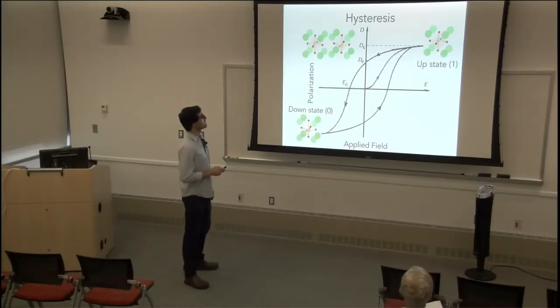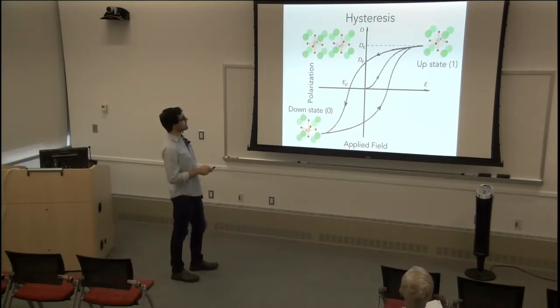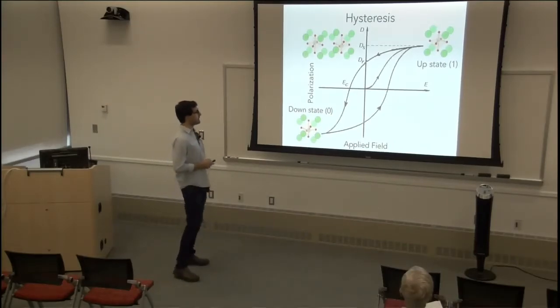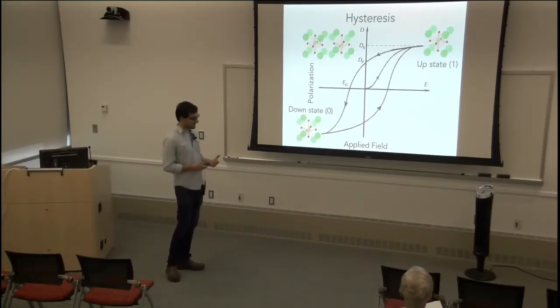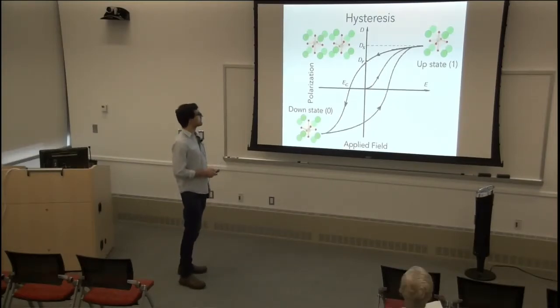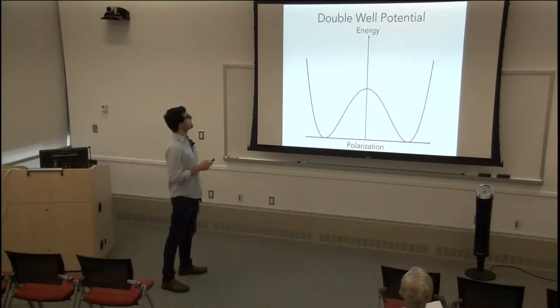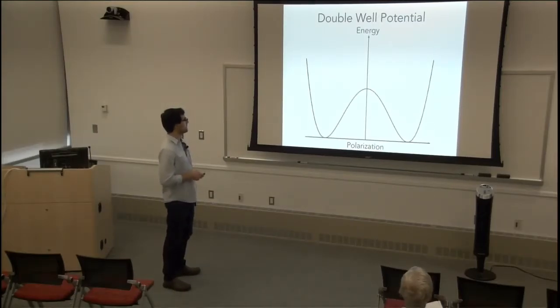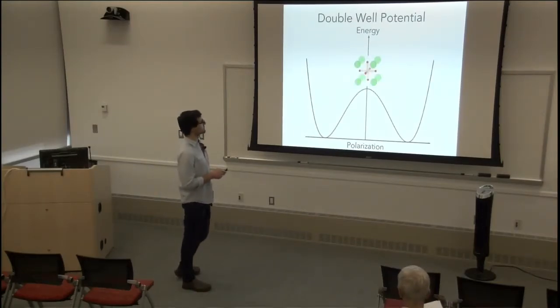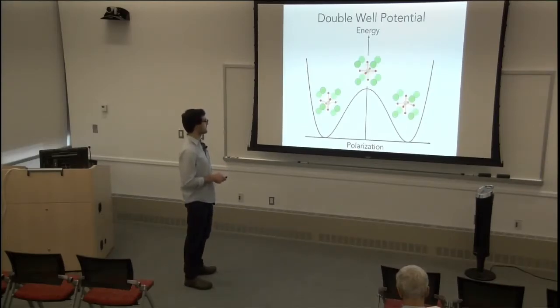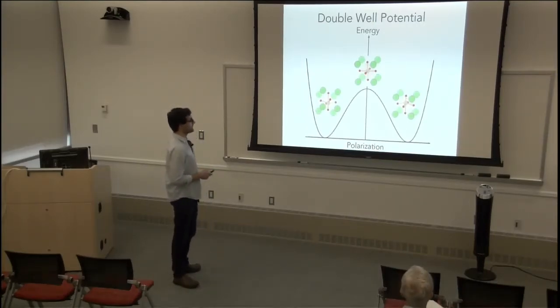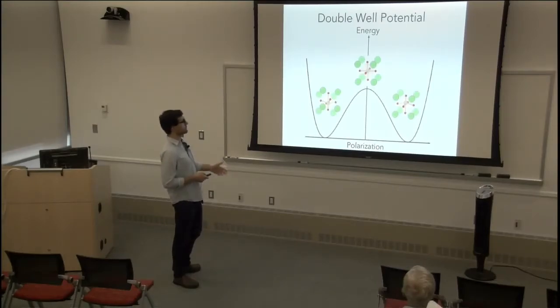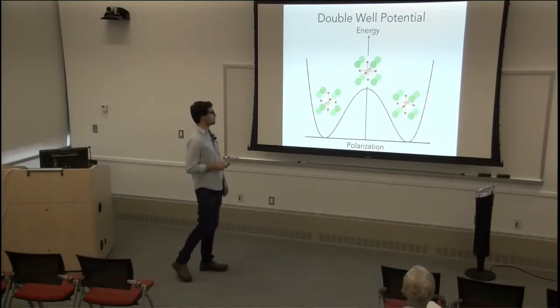Okay. The one thing that you also notice is that as we move on this curve, we never actually get back to 0 polarization. And that tells you something in terms of the energetics, which is what physicists like to think about. That means the state that has no polarization must be quite unstable relative to these two states. So we can think about this from a diagram, and this is what we call a double well potential. You have your centrosymmetric state that has no polarization with the higher energy, and you have your two states, either up or down, at the bottom of this well, which are your stable states. And of course, the well is symmetric, because these things are related by mirror symmetry. So if you flip this one, you get to this one, and there's no real reason why one should have a lower energy than the other.